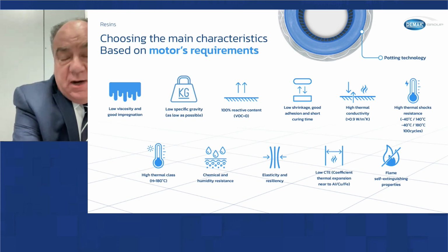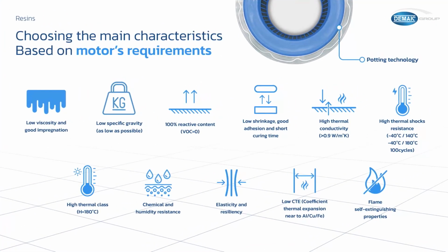Our R&D is very strong in this field, and we have developed several formulations, epoxy and polyurethane, room temperature and heat curing, in order to meet all possible customer requests and possibly also to anticipate some customer requests. As a main characteristic of the system, we look for low viscosity and good impregnation. It is a very important characteristic because it's necessary to fill the space completely, avoiding leaving air inside.